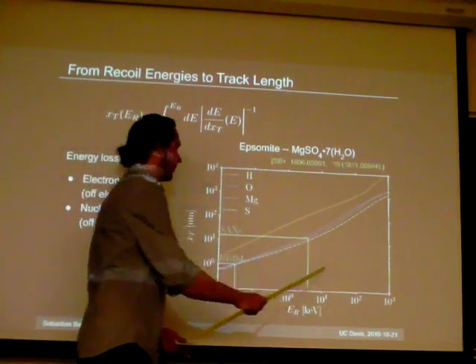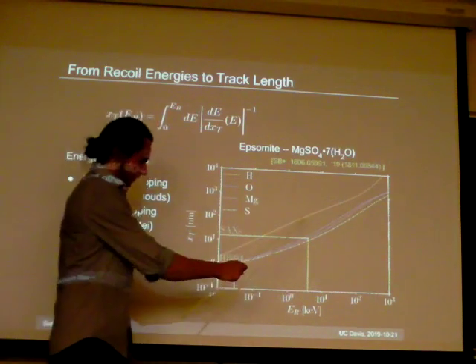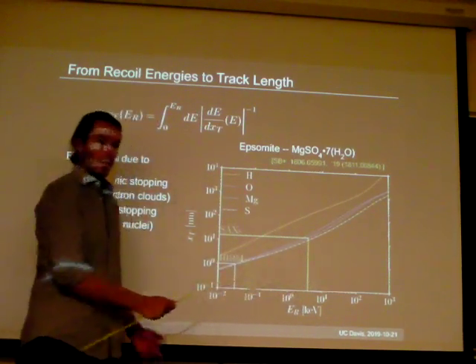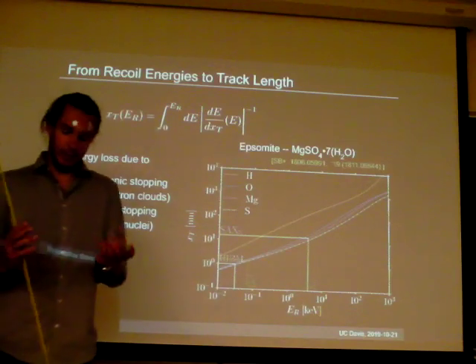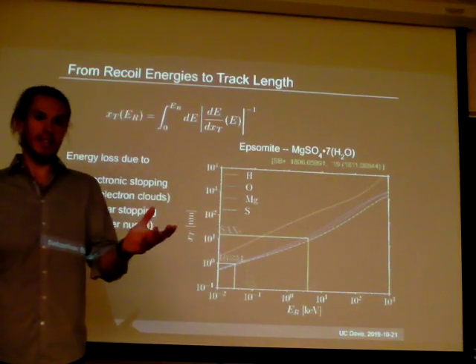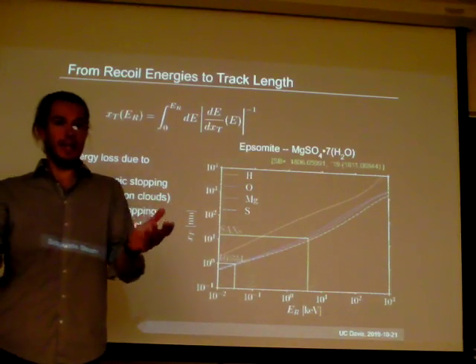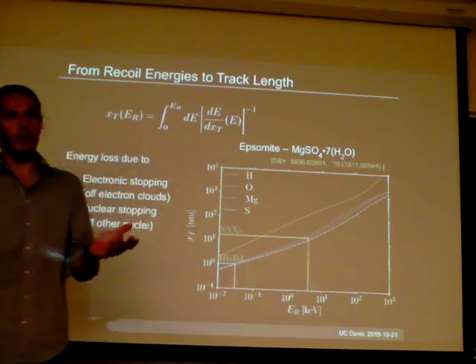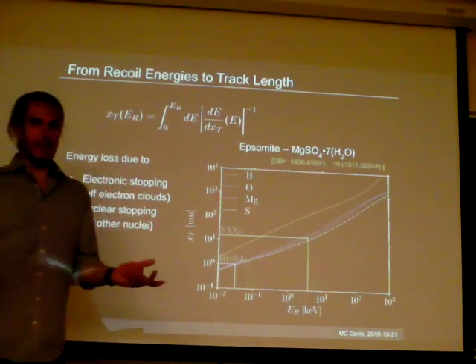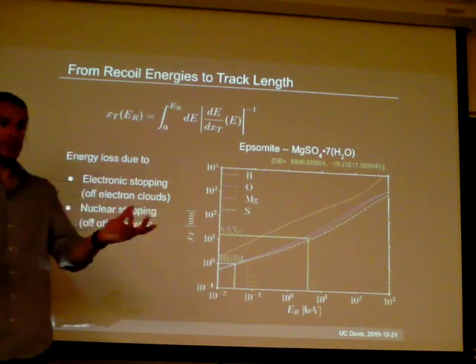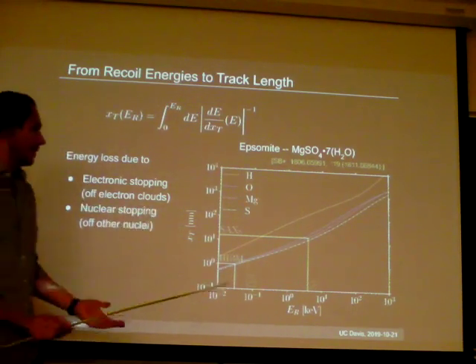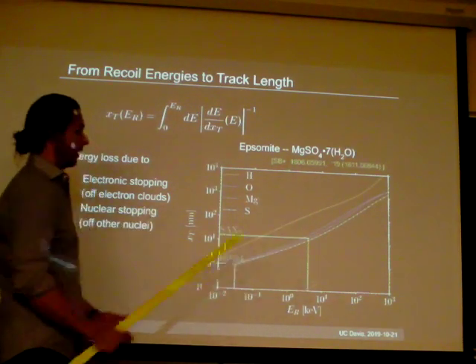And there is some width in this. But you get a good idea of what is the recoil energy, right? Which now allows you to imagine, so imagine you measure a bunch of tracks, right? Now what you're going to gain by this is energy resolution of your signal. Whereas in a direct detection experiment, you count how many photons you get, and that gives you the energy resolution, for example. Here you count the tracks and it allows you energy resolution.